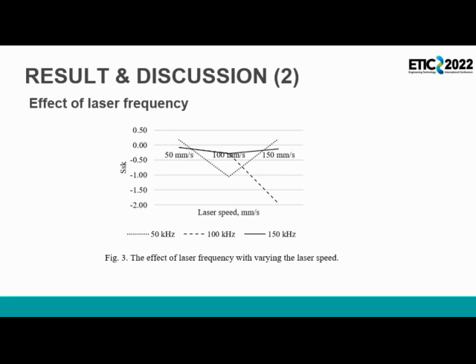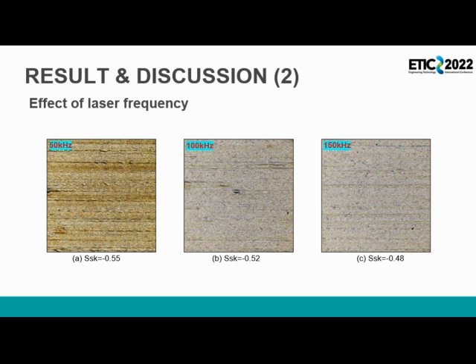Based on figure 3 above, the laser frequency at 150 kHz gives a consistent value even when the laser speed is increased at constant laser power of 12 watt. The study from Xi also found the same result, that the higher laser frequency will decrease the effect of the heat zone and a better processing effect can be obtained, such as microstructure and surface roughness profile.